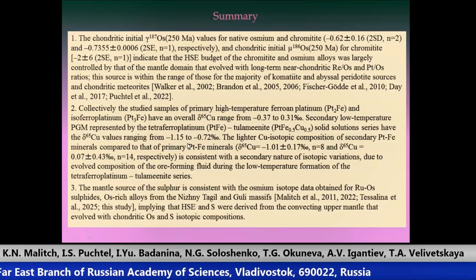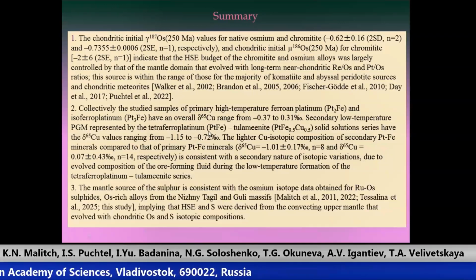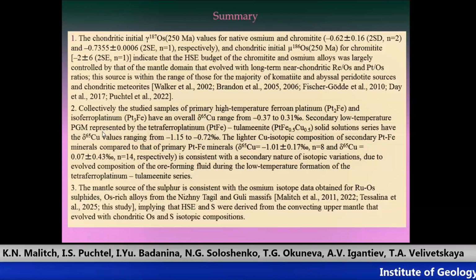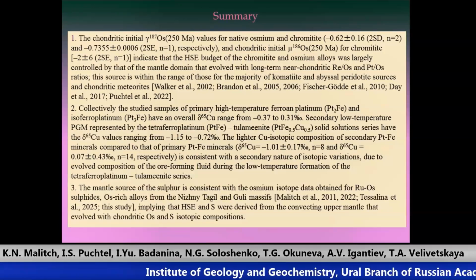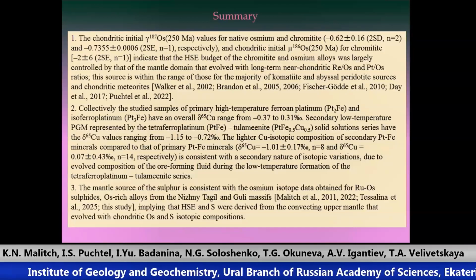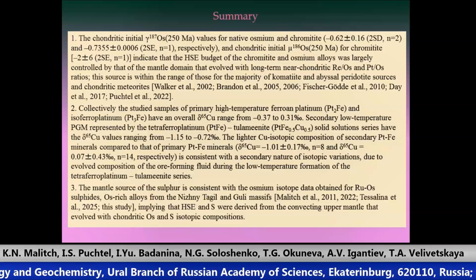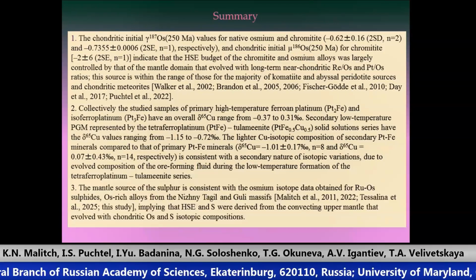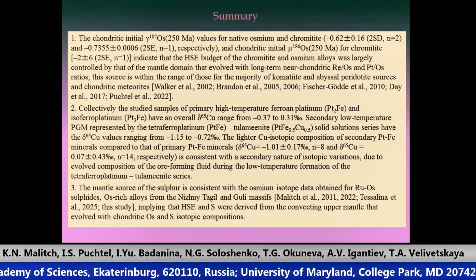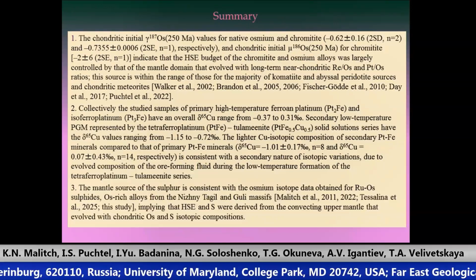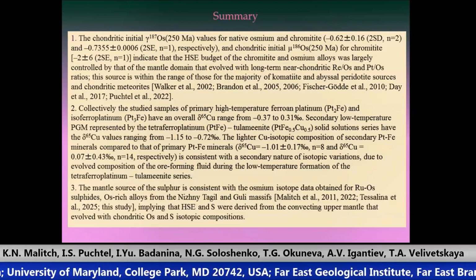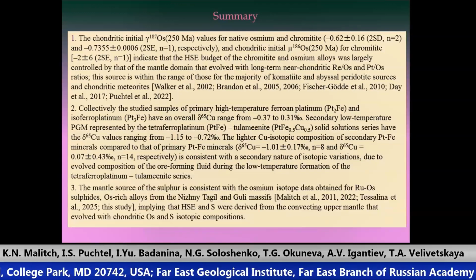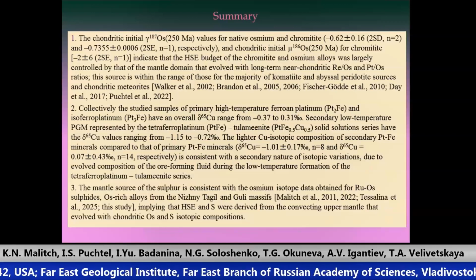Second, collectively, the studied samples of primary high-temperature ferroplatinum and isoferroplatinum have an overall δ65Cu range that clusters around 0. Secondary low-temperature PGM, represented by the tetraferroplatinum-tulameenite solid solution series, have copper isotopic composition ranging from minus 1.15 to minus 0.72 per mil. In this context, the lighter copper isotopic composition of secondary Pt-iron minerals compared to that of primary platinum-iron minerals is consistent with the secondary nature of isotopic variations due to evolved composition of the ore-forming fluid during the low temperature formation of the tetraferroplatinum-tulameenite series.